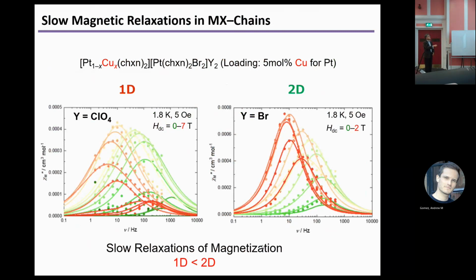ion. So the one-dimensional compound shows a slow magnetic relaxation. The two-dimensional one shows a slow magnetic relaxation. This is due to the one copper ion showing a slow magnetic relaxation, working as a molecular spin qubit. So then the two-dimensional is longer lifetime compared to one-dimensional due to the rigid lattice.